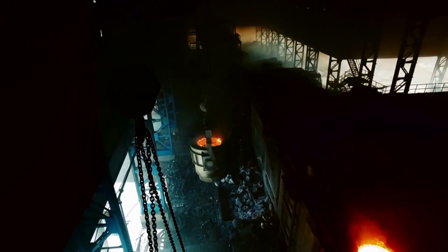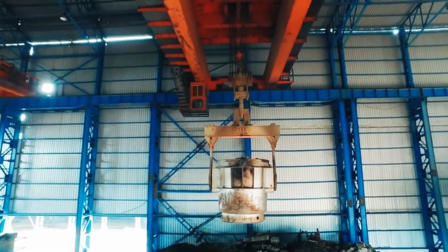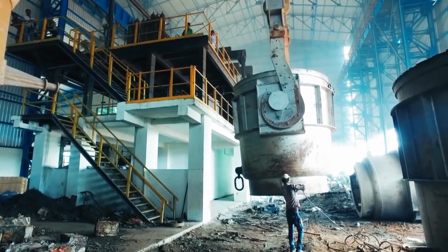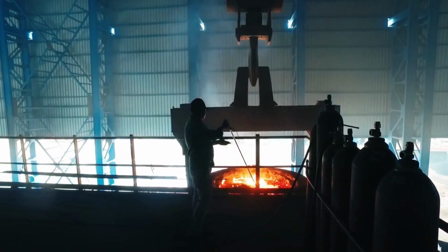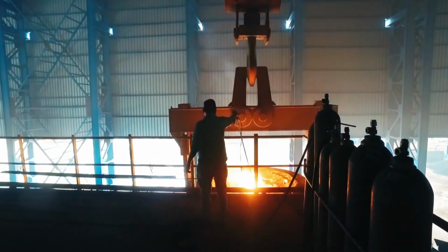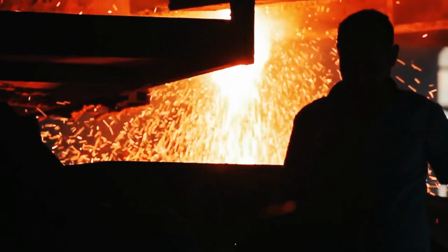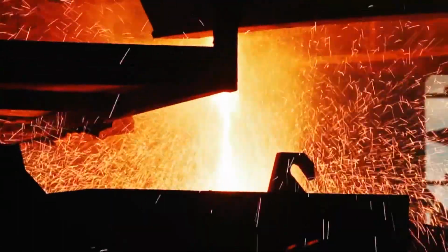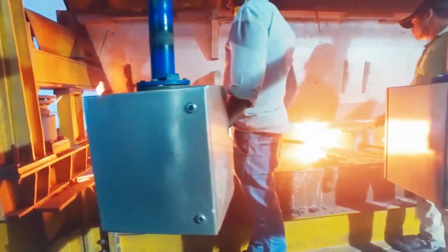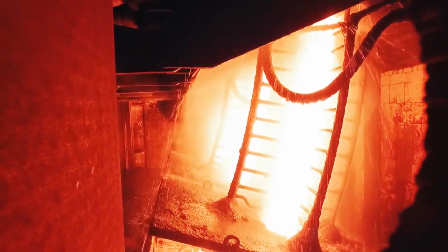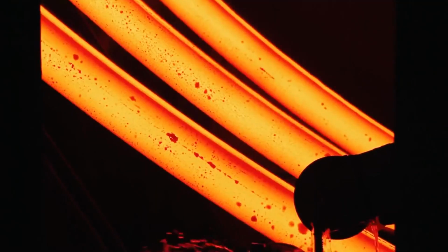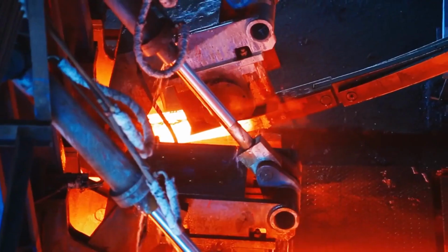After the molten metal has been extracted from the crucible onto the casting ladle, it is purged with nitrogen to gain homogeneous chemistry and uniform temperature throughout the ladle. The ladle is then taken to a continuous casting machine where it's placed onto the ladle car. The material then passes from the ladle to tundish and from tundish to mold tubes. This sequential casting begins from all three strands.